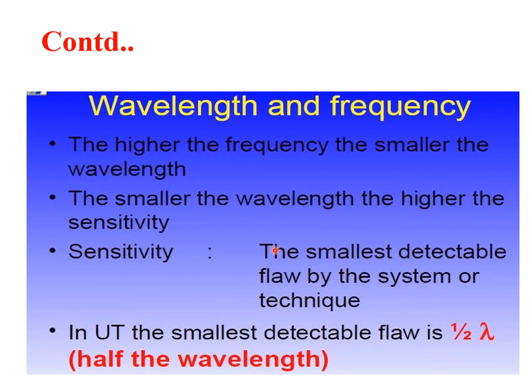So what we require here is, as the frequency is increasing, the wavelength is decreasing. So as the wavelength decreases, the sensitivity increases. So in order to get proper sensitivity, we have to go on increasing the frequency, but there is a limitation on increasing the frequency for the material. In ultrasound testing, the smallest detectable flaw is half of the wavelength, that is half of lambda.